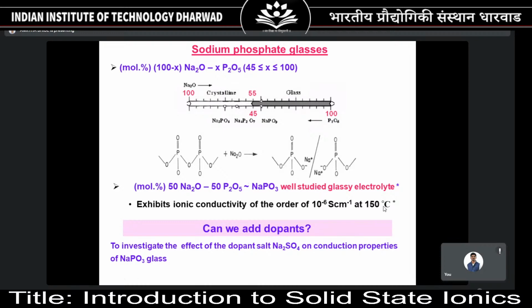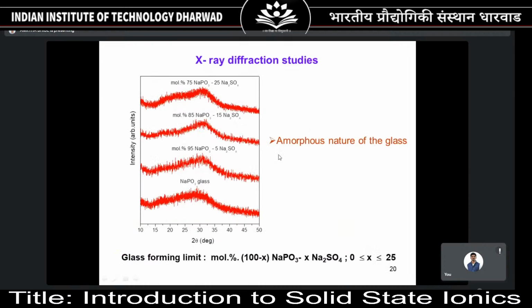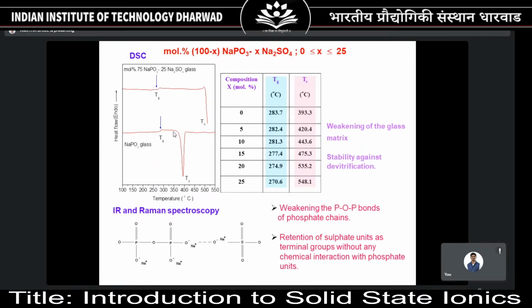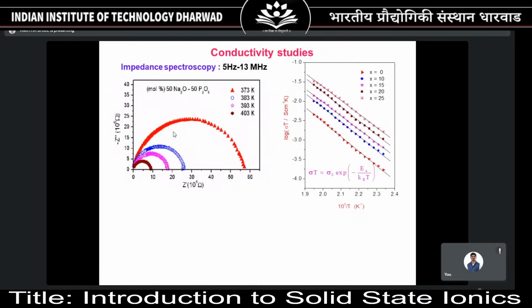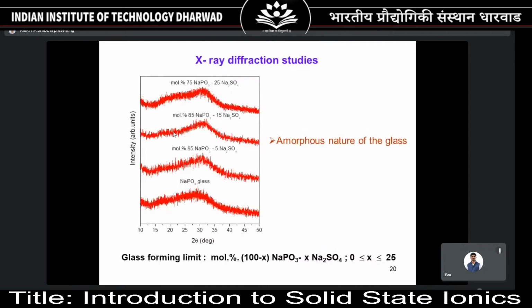Can we have dopants here? Yes, we can have dopants, and I am also showing some characteristic XRD graphs of these glasses. As we told, there is no long range order. You can see a big hump in the XRD, and we keep on adding sodium sulfate as a dopant, in different weight percent, up to what I could add to the sodium glass. Now, what is the result of having sodium sulfate in the glass? I can show the next slide, or I'll give the outcome a little later.